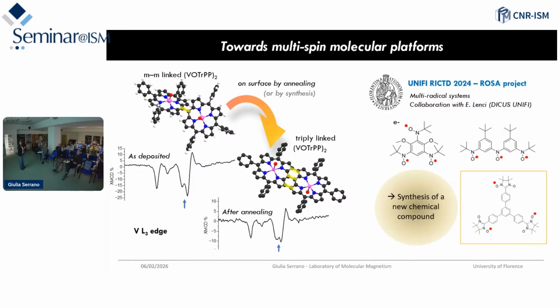Of course, if we change the ion with cobalt or copper, we can try to maximize this exchange interaction. But as soon as we go farther apart between the two species, the exchange interaction will either pass through something that magnetically connects these two ions. That's why a radical would be important, or through the surface. This could be also the case. We would need a very good STM to do that.